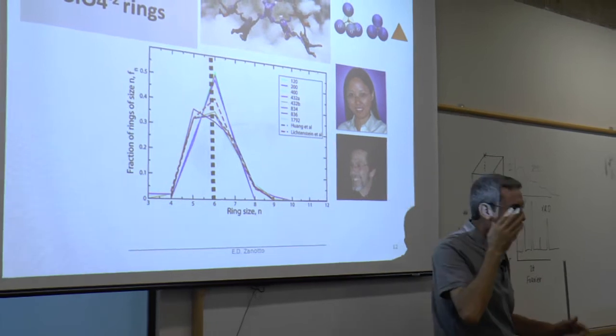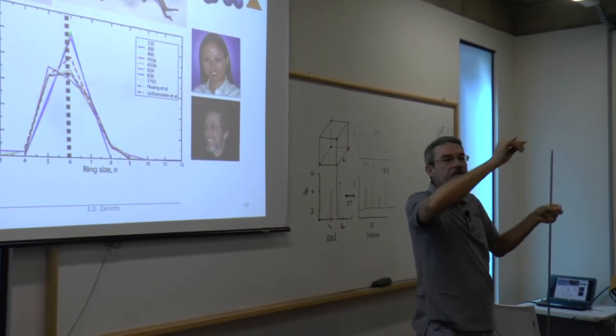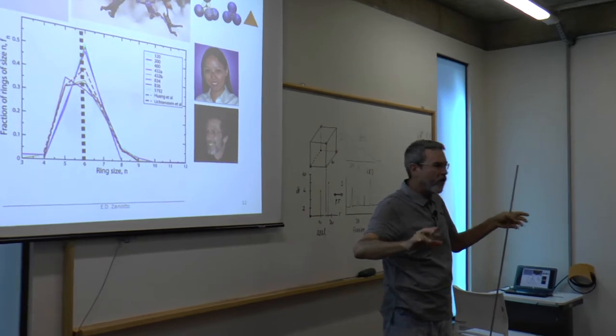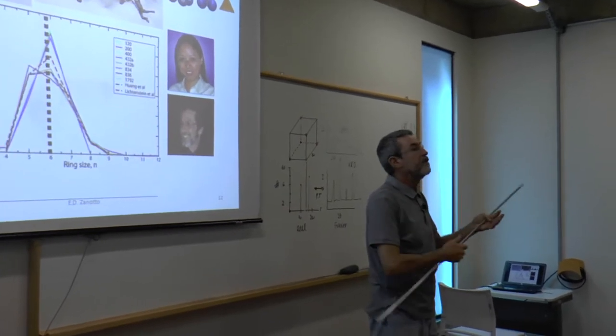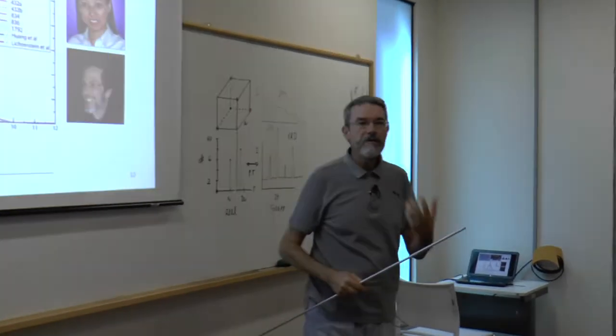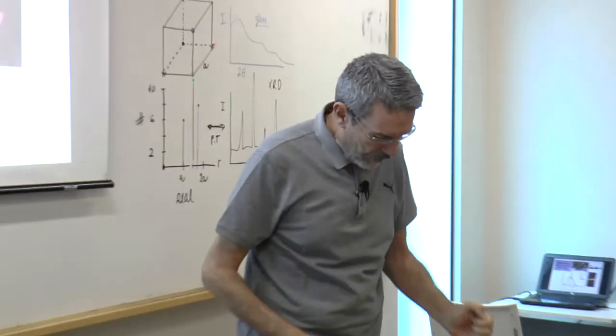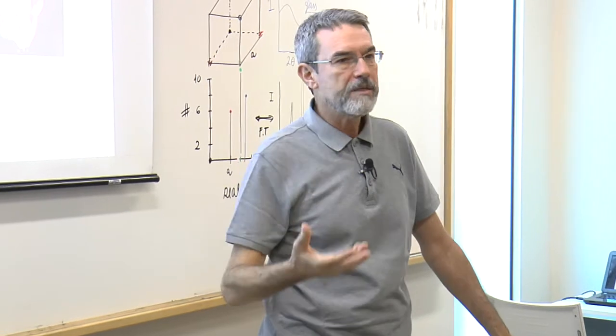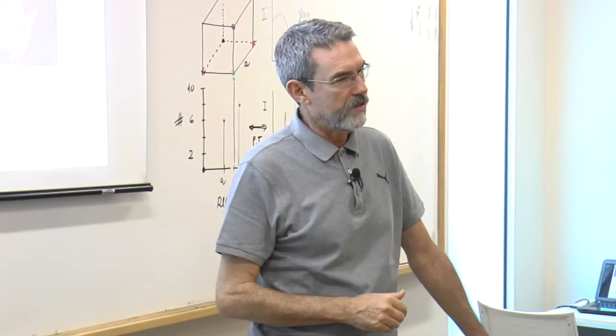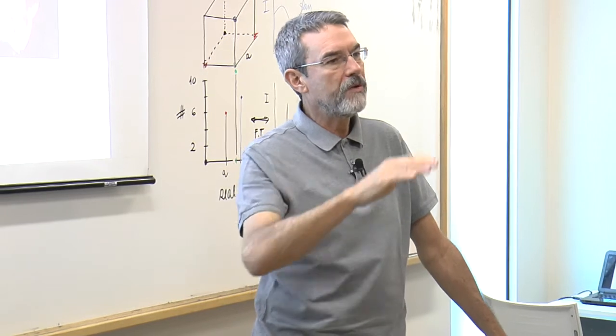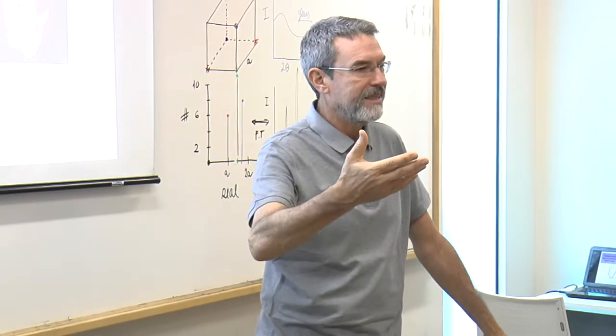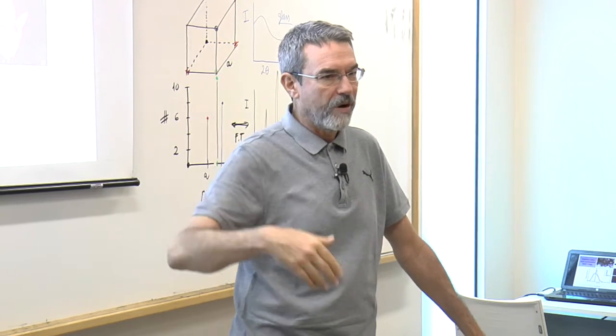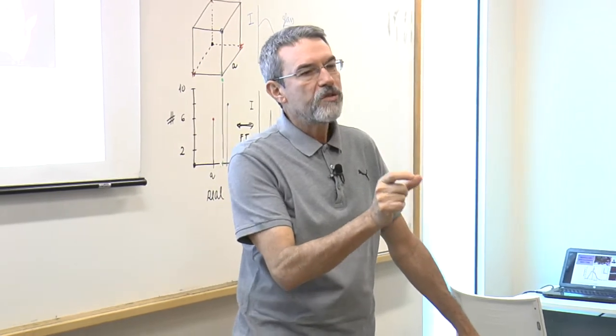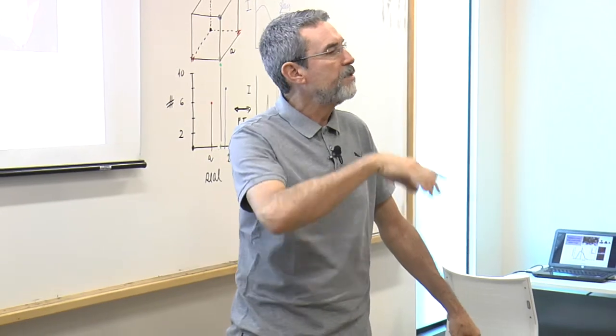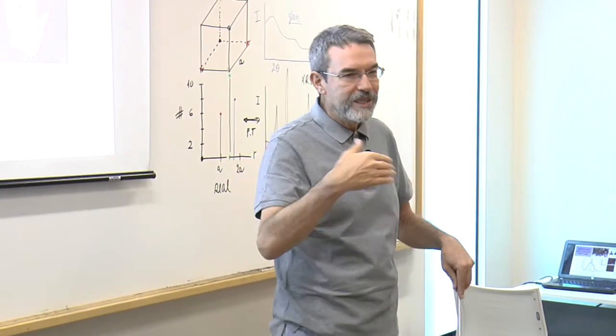6 is the number for the crystal phase. So the average for the glass is also 6, or close to 6. But there is a distribution. So this is the kind of information that you need to distinguish the structure of a glass from the structure of its isochemical crystal phase. A distribution of rings, the short versus medium range distances that I have shown before, distribution of angular distances, and so on.